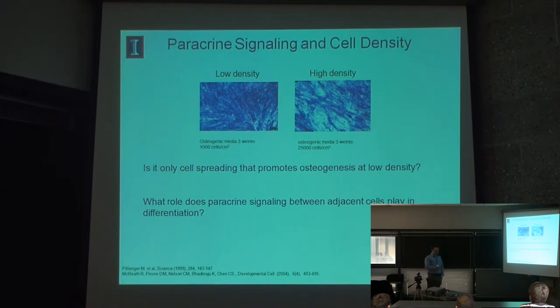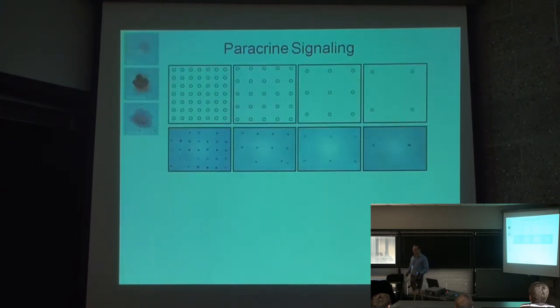So we wanted to look at paracrine signaling, and the way we devised to do this, very simply, is by patterning cells at a different distance. So you can change the diffusional path length between the single cells, going from about 100 microns separating every cell to 200, to 400, to 800. So they're nearly a millimeter apart in your dish. And so we did the analysis that way, and we dumped in the chemicals as before.